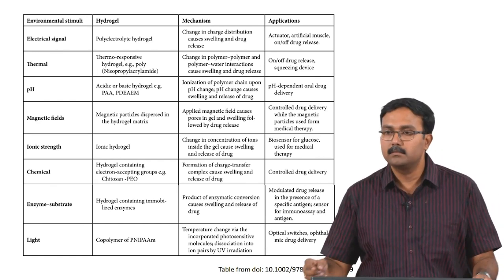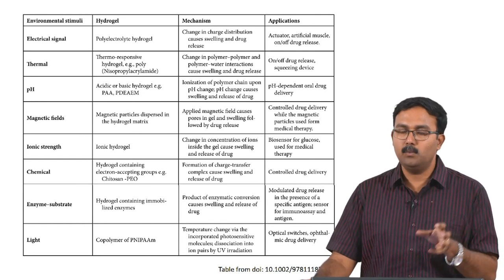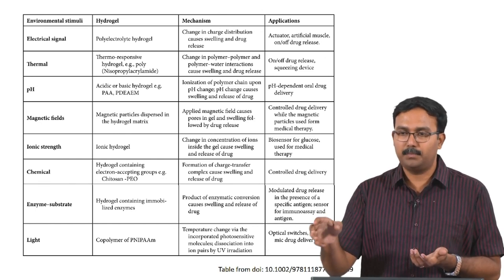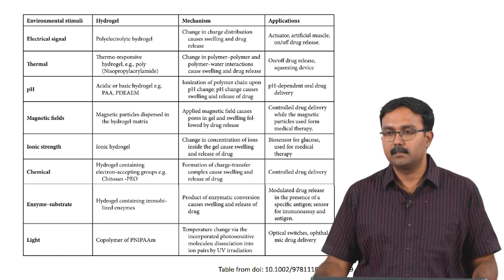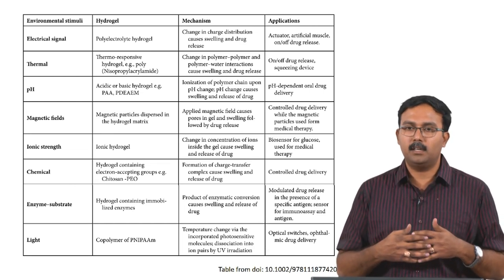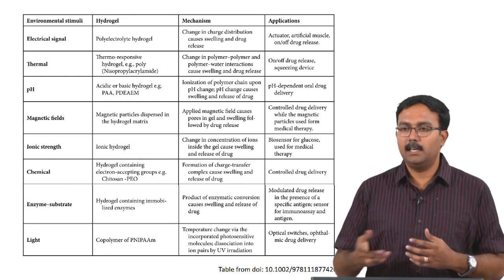Student question: Are these smart hydrogels made from special polymers, or can regular hydrogels be modified to have smart properties? They have to have some monomer or side chain which responds to the stimuli. A regular PVA hydrogel cannot behave like a smart hydrogel on its own. If you create side chains which provide stimuli responses then you can do it, which means you are modifying PVA into some other polymer first. Student: Will surface modification help? For a hydrogel, surface modification would not be very helpful because a hydrogel is a 3D structure. Surface modifications are done for implanted polymers, whereas for polymers fabricated into something else you need chemical modification of the entire material - surface modification alone cannot address the required needs.